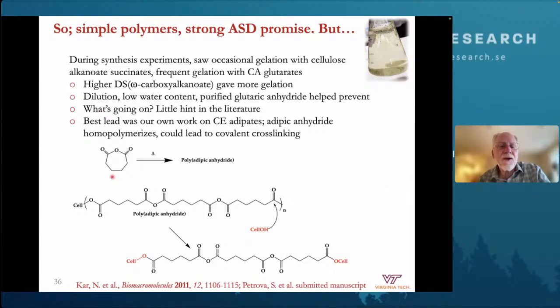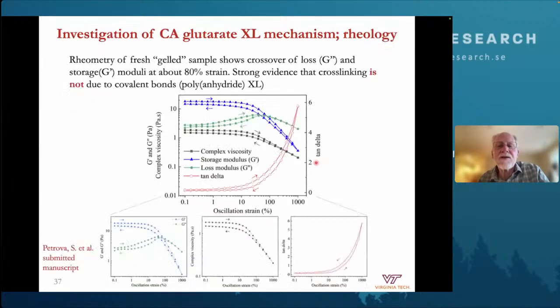We had previously done work on cellulose adipates. Adipic anhydride has a lot of strain energy in the ring, and it tends to homopolymerize. We were able to prove in that work that the mechanism of gelation with adipic anhydride was that you grew oligoadipic anhydride side chains off of cellulose. Another molecule of cellulose came along, and if it reacted at the anhydride linkage closest to cellulose, that would cause a cross-link. So that's what happens with adipic anhydride, and we thought probably that's what's happening with these glutarates and succinates.